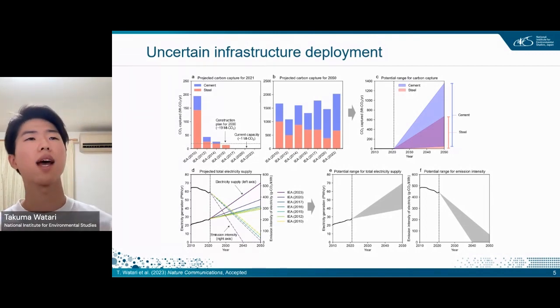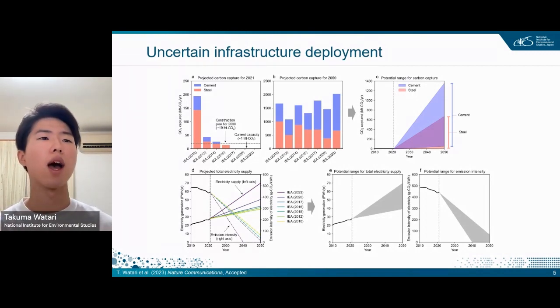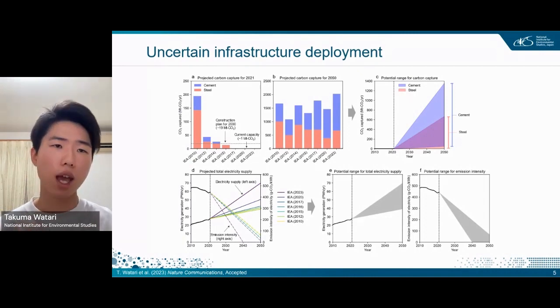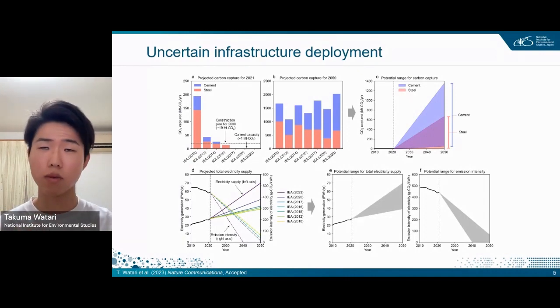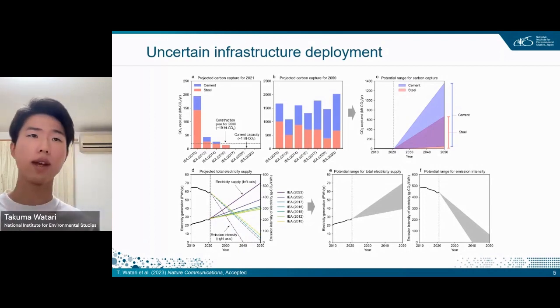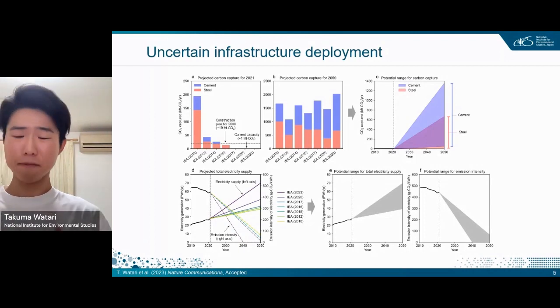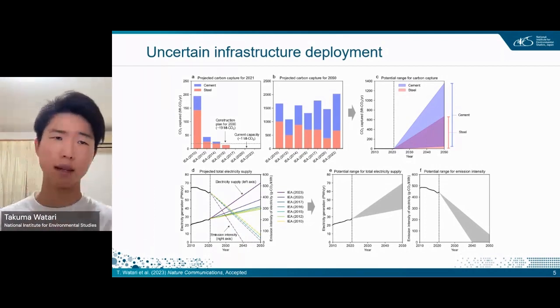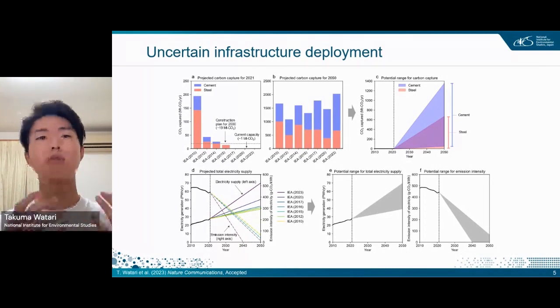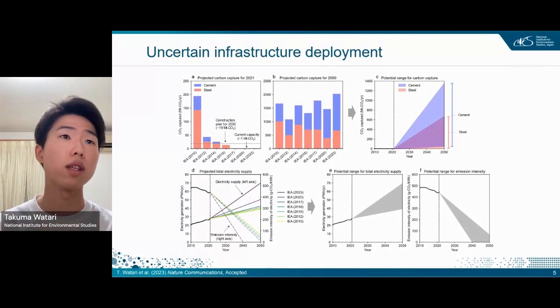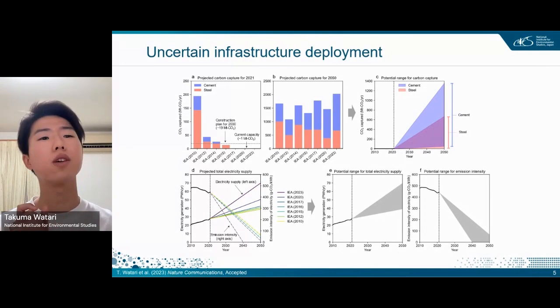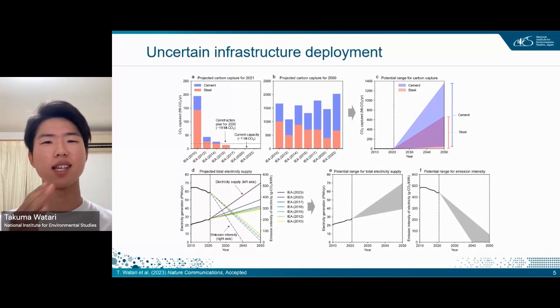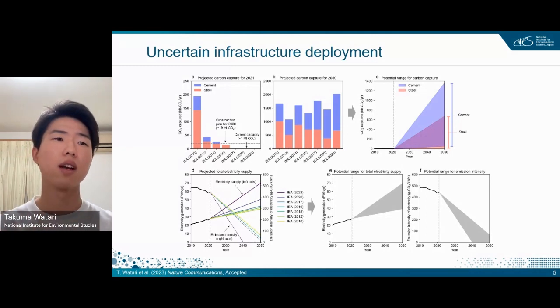Looking at the left side of the figure, about the IEA projections for carbon capture and storage, for example, we see that the 2010 IEA report assumes that the CO2 capture for the steel and cement sector would reach roughly 200 megatons CO2 in 2021. But because our progress is too slow, they have adjusted their projections over time. So we have a clear downward trend on the left side of the figure.